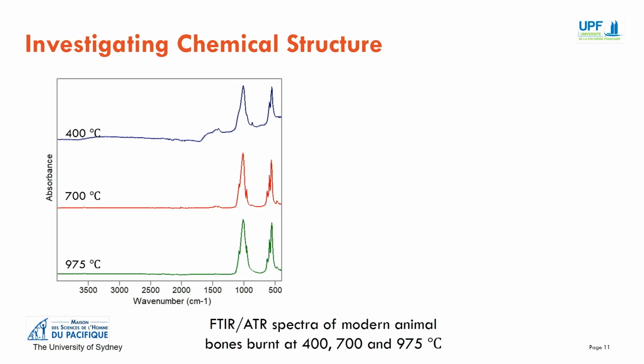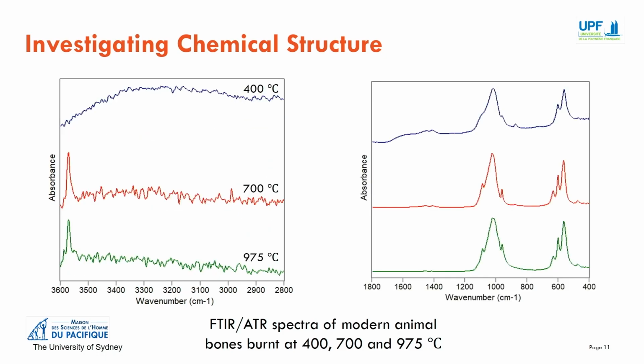This first figure presents the ATR spectra collected using a portable FTIR spectrometer from 3 samples of animal bones subjected to 400, 700, and 975 degrees Celsius. The next 2 figures are an expansion of these spectral regions. The bands marked on the figures at 3,570 and 630 wave numbers are assigned to the hydroxyl stretching and libration modes, which are attributed to a heat-induced reorganization of bioapatite's microcrystalline structure.